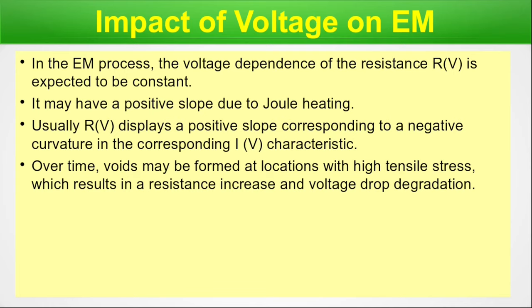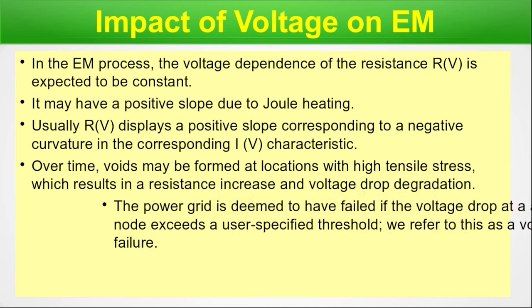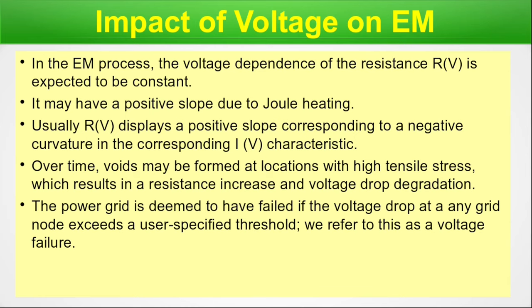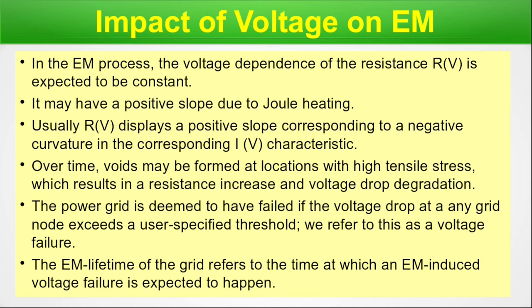Due to electromigration, two things happen. One, a hillock is created or a void is created. Now, if a void is created, what will happen? The cross-section of the current-carrying metal or via will get reduced and hence the resistance will increase. If the resistance increases, the voltage drop degrades. So this is the way things are happening. The power grid is deemed to have failed if the voltage drop at any grid node exceeds a user-specified threshold. We refer to this as a voltage failure. These specifications come from the design as well as from the DRM. These things have to be maintained. The EM lifetime of the grid refers to the time at which the EM-induced voltage failure is expected to happen. So this is the entire picture of the failure of a power grid in terms of voltage. We are done with this particular slide, so let's move on.